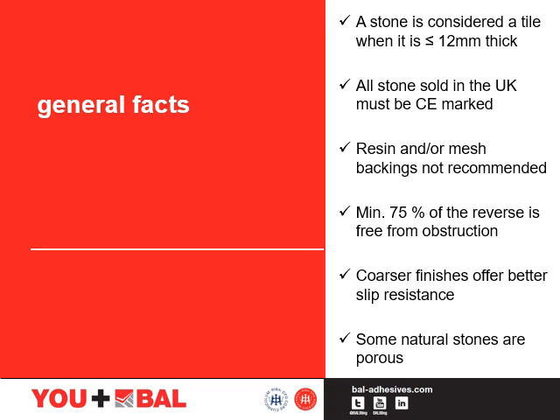All stone sold in the UK must be CE marked and this includes all imported stone. Resin or mesh back stone is not recommended for use when tiling. These backings are often used to strengthen the tile during transport. However, these can impinge on the bonding of stone tiles. In order to use these tiles, the backing must be completely removed. A minimum of 75% of the reverse of every tile must be free from bond inhibiting materials so the adhesive can make contact with the tile back.